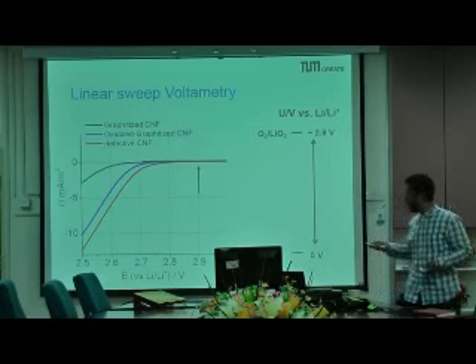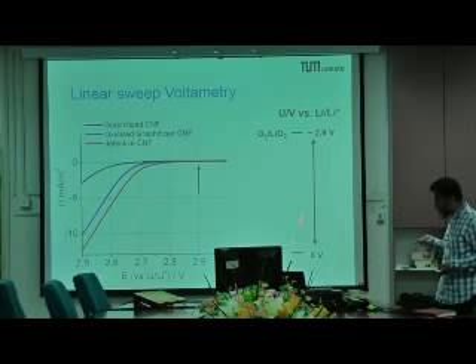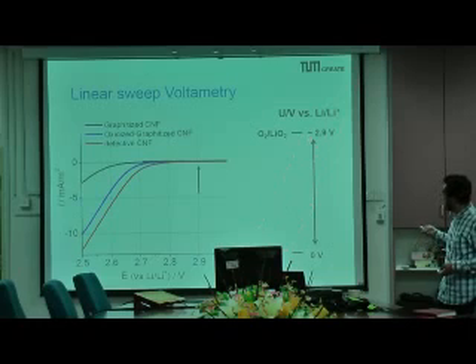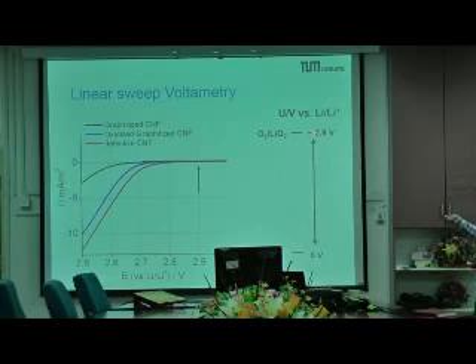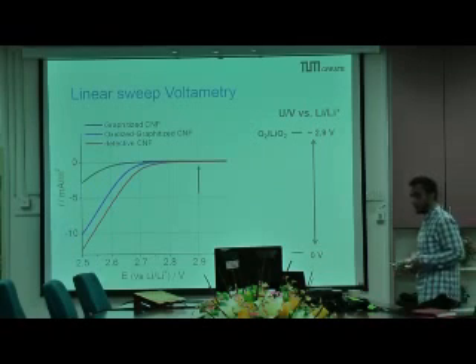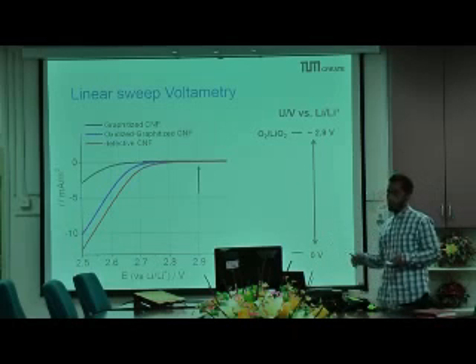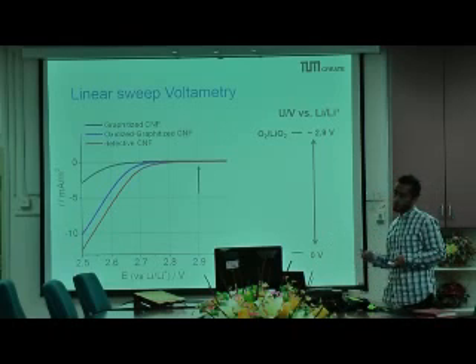The consequence of this in a battery is that you lose the energy of this material, because the equilibrium potential is about 2.9 volts. If you keep going down to gain current, to overcome the barrier, either kinetics or resistance drop, then you're working in a way which is not desirable in a battery. You want to have as minimal overpotential or resistance as possible.